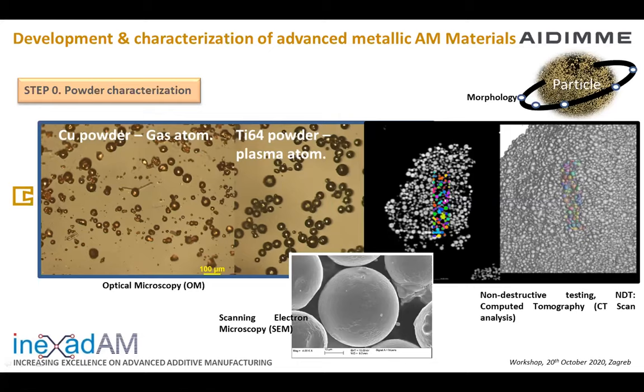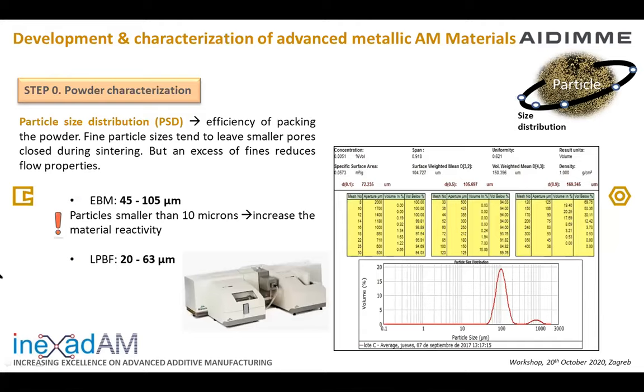We also characterize the powder by non-destructive testing. It's also possible to see some irregularities and defects, and to quantify them. So we combine conventional techniques together with this one. The particle size distribution is related to the efficiency of packing the powder. Fine particle size tends to leave small pores, which are closed during sintering. However, an excess of fine particles reduces the flow properties. So you can see how each of them affects the other. Here you can see the usual powder particle size distribution for the EBM technology and the laser powder bed fusion.